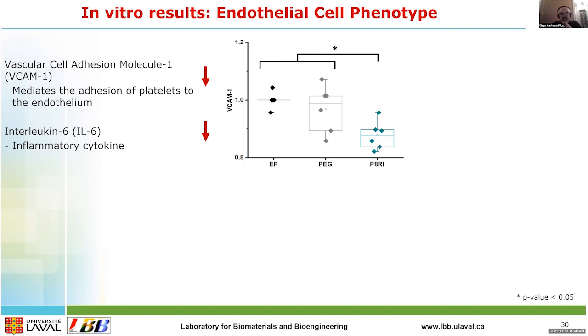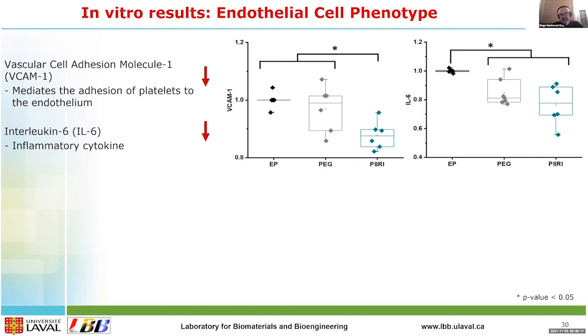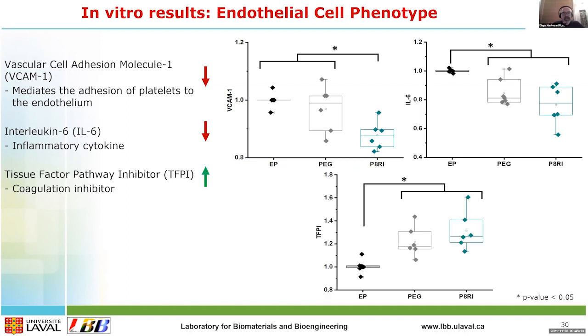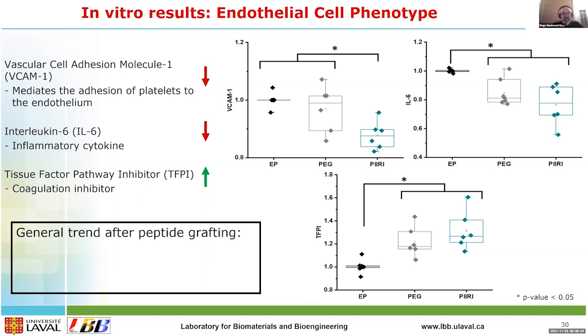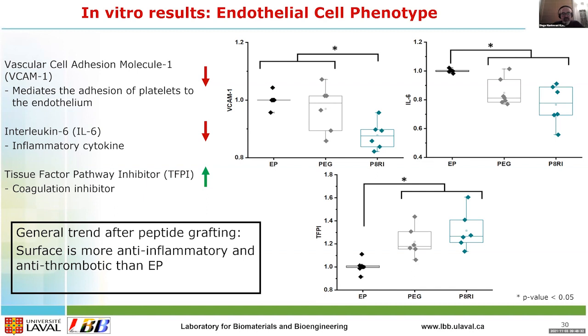So decrease the thrombogenic potential. Interleukin, which is an evidence of inflammation, decreased, and the tissue factor pathway inhibitor, the TFPI, which is the coagulation inhibitor, so inhibition of coagulation is enhanced. And finally, the peptide grafting in vitro revealed that the surface was more anti-inflammatory and anti-thrombotic than the electropolished one. This is exactly what we expected.